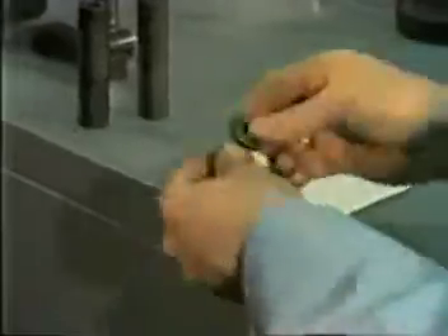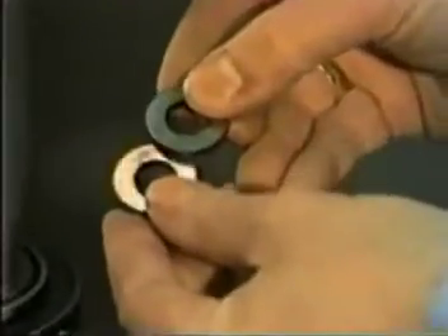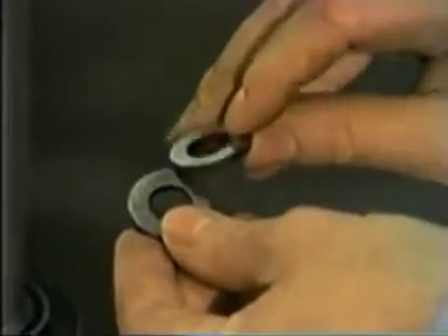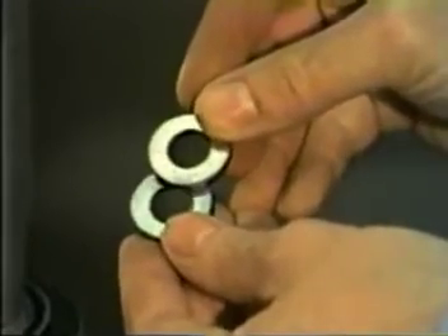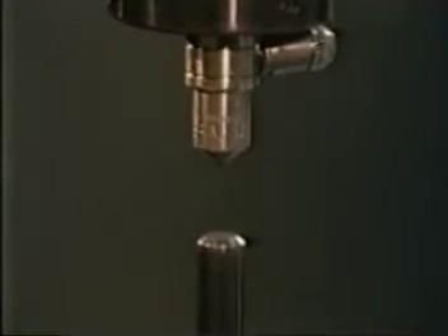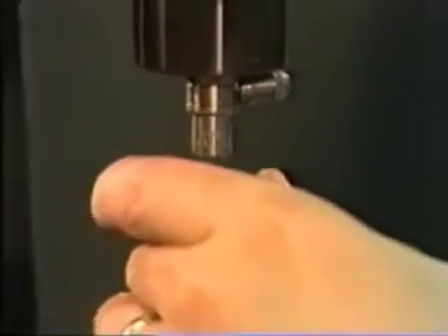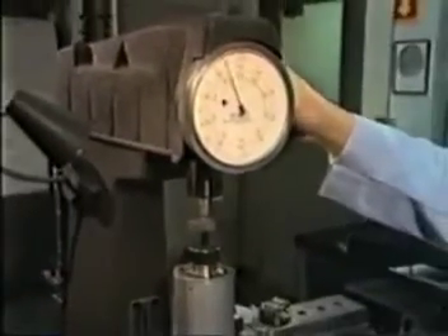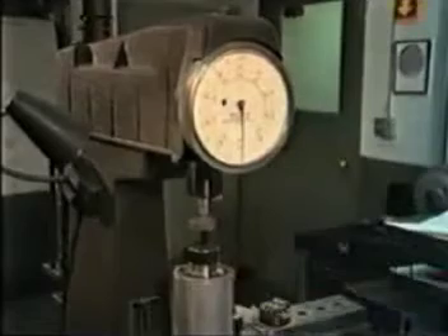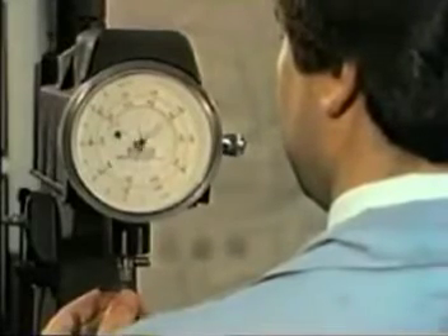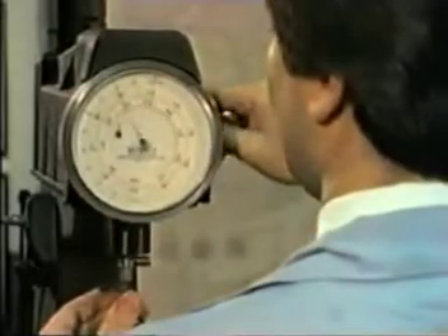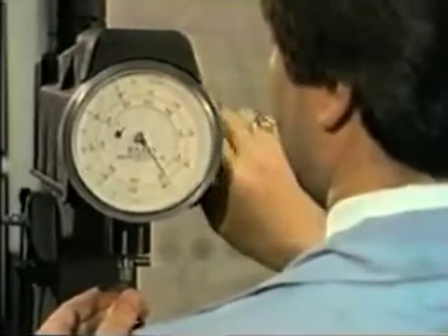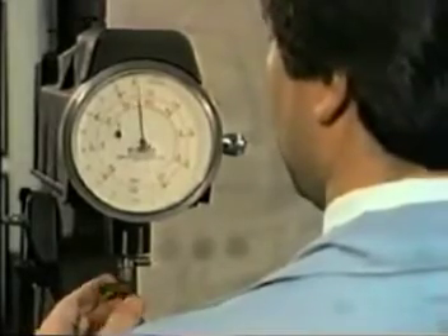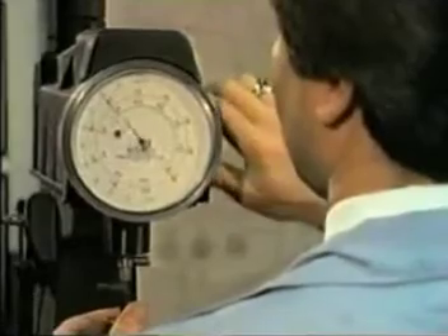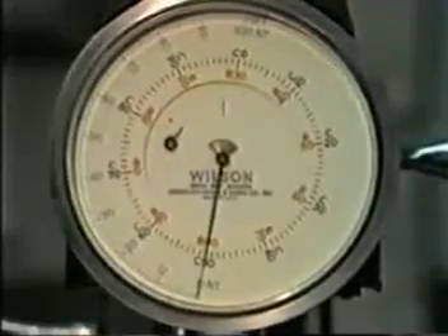It is essential to have parallel and clean surfaces on which to make a test, as the diamond must penetrate the material squarely in order to get a proper reading. After selecting the part to be inspected, it is elevated on an anvil and is brought into contact with the brale. The machine is zeroed out and the appropriate load weight is applied by tripping the handle. When the indicator comes to a stop, the hardness is read directly from the dial on the instrument. While there are several scales available on most Rockwell machines, the most frequently used is referred to as the C scale, and the higher the C scale number, the greater the hardness.